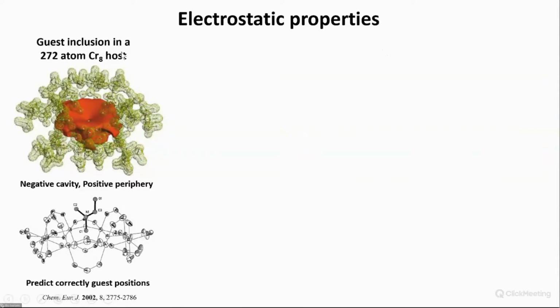I still like it very much because at that time, I thought it was one of the biggest studies done, biggest molecules. It's like 272 atoms and 8 chromium atoms. And at least 20 years ago, that was a good demonstration of synchrotron radiation that I really like. And if you get the electron density, you can plot the electrostatic potential. And in here, it was very clear that you have this negative cavity and the positive periphery.